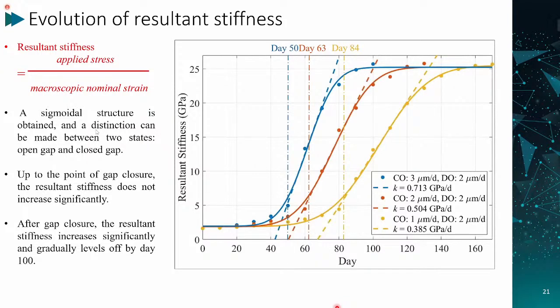We calculate the resulting stiffness. This value was obtained by applied stress divided by the macroscopic nominal strain. We can see from the left figure, the sigmoidal structure is obtained, and a distinction can be made between two states, open gap and closed gap. So up to the point of gap closure, the resulting stiffness does not increase significantly. So this region, we call it an open gap zone. And after the gap closure, the resulting stiffness increased significantly and gradually levels off after 100 days.